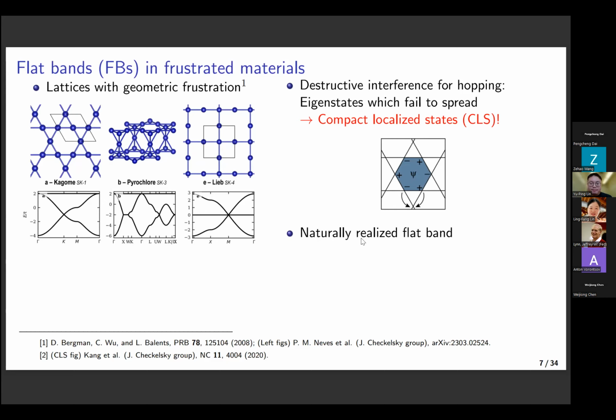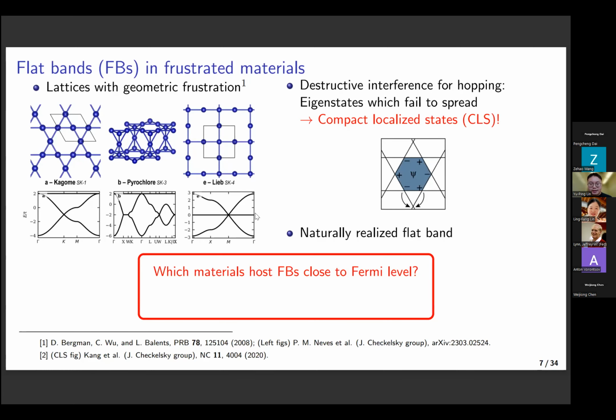So the kagome lattice, for example, will host a natural flat band from the frustrated hopping. And similarly, we can do the same thing for pyrochlore and Lieb lattices and show that the flat band can come from the compact localized state. So now we see that frustrated materials are a promising family to realize flat bands. And an important question is, given these frustrated materials, which ones will host the flat band close to the Fermi level?